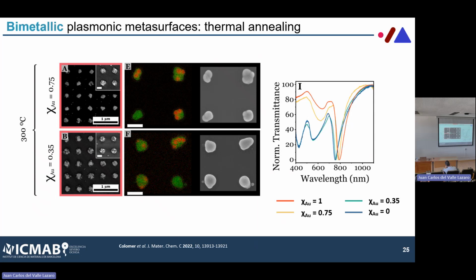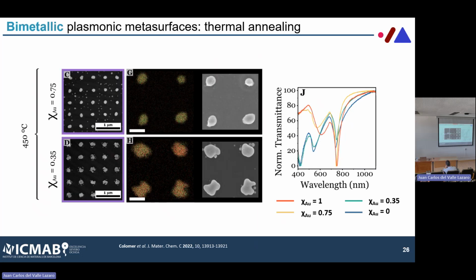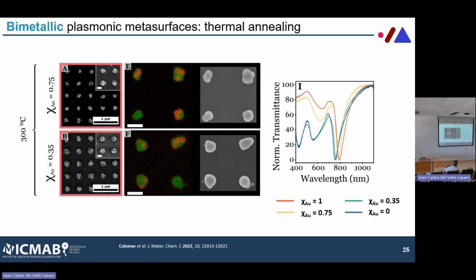The thing that is very interesting here is that if you look at the optical properties, we see that the system that contains a mixture, just 25% of gold basically, is enough to avoid the deformation of those items that you've seen in the previous slide for silver. And so we are actually able to improve the optical properties.